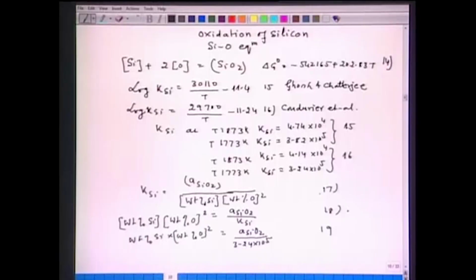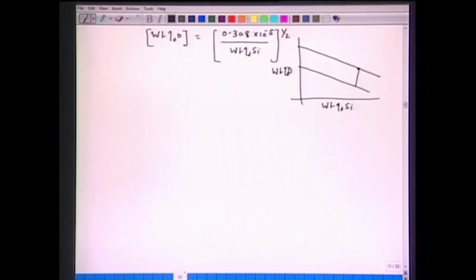Also, if we see this equation number 17, we see that if we decrease the activity of SiO2, then the silicon reaction is favored. So, what we can conclude from here is that in steel refining silicon oxidation is very fast, and silicon oxidizes before any other impurities, because the heat of formation of SiO2 is very large, that means a highly exothermic reaction.